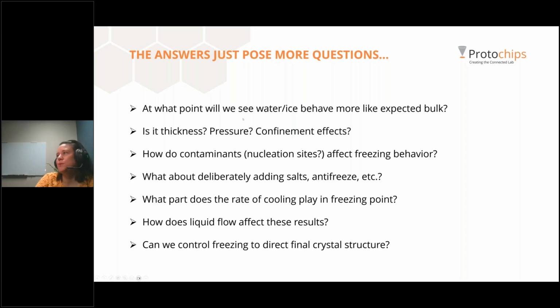Like, at what point do we see water and ice behave more like bulk? I had a liquid layer that was greater than 1 micron, but it was still freezing at a lower temperature than 0. Do I have to go even thicker? What about 5 microns? Will that freeze at 0? Is there something else happening? Is it just the liquid thickness, or is the cell pressurizing in some way?